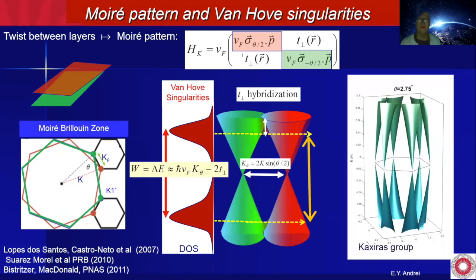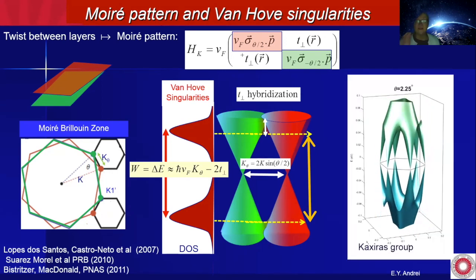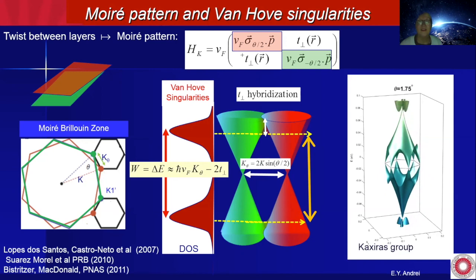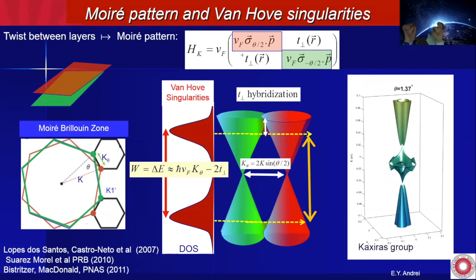Let me do a little simulation here. This is a simulation of the band structure as a function of twist angle, and you see as you reduce the twist angle, the band becomes flatter and flatter and flatter until you reach 1 degree, which we call the magic angle, where it's completely flat. And as you continue to decrease the twist angle, it starts swelling up again.